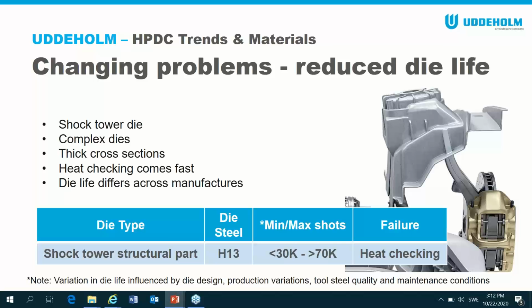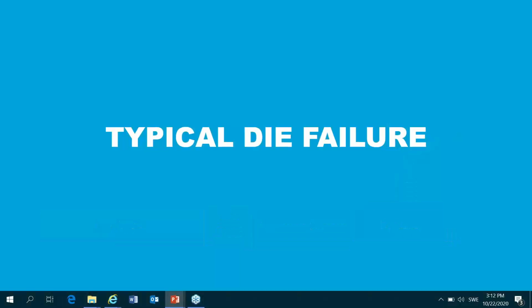There's one market which stands out globally, and that's Germany here. Germany has some of the best die life I've seen when it comes to high pressure die casting. They use an H11 type normally. But again, they're having to regrind the panels quite early on. So the total die life is probably quite good, but there's a constant reworking of the panels, which is of course very expensive. And interestingly, that tends to start around the 40, 50, 60,000 shot area, depending on how bad it is. So we've seen the trends and an indication of the type of challenges that you're going to face in these certain parts.